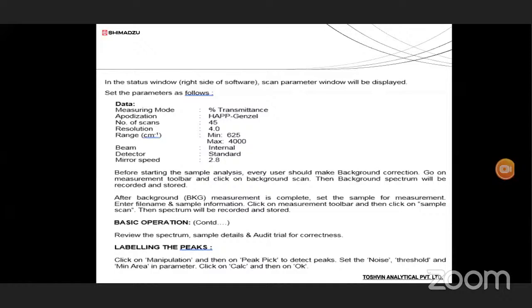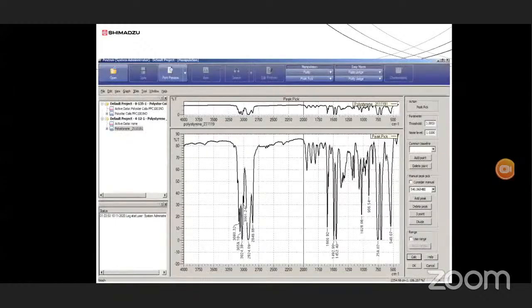After setting the parameters, we do the baseline or background correction. After running the background correction, you put your sample in the sample compartment, placing it on the diamond ATR, and run the sample. We get the spectrum of that sample.